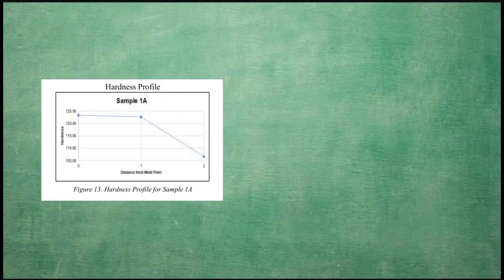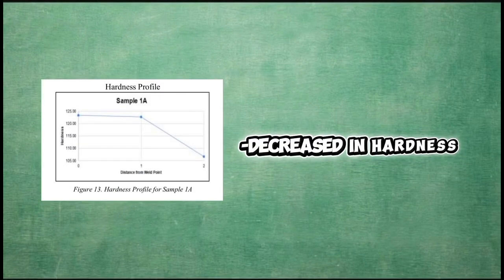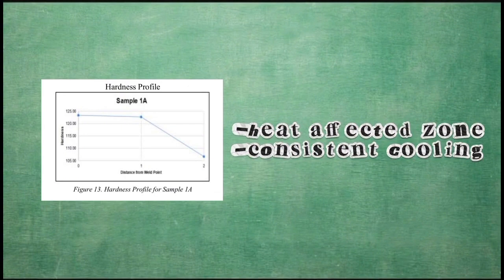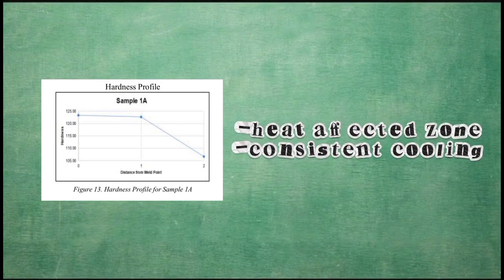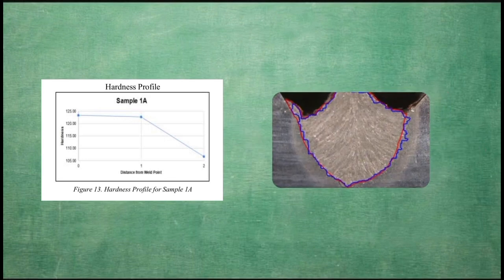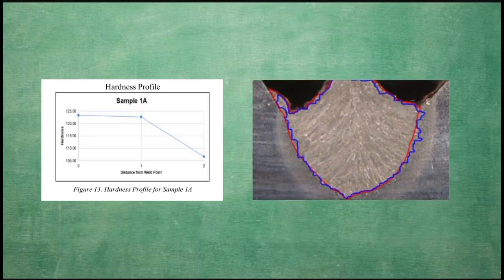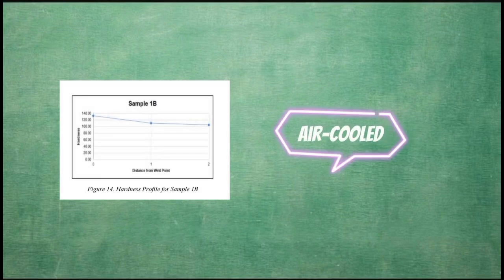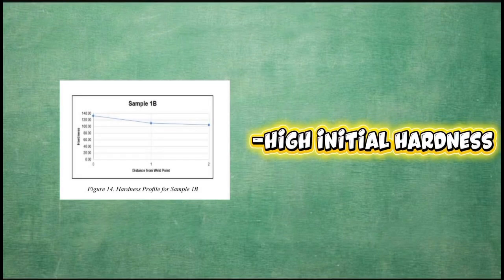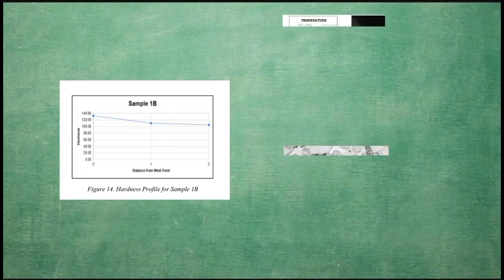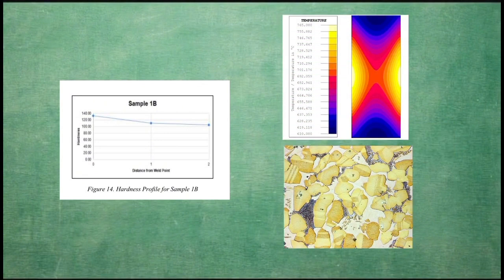For the discussion of results, we have sample 1A, air-cooled, which showed a gradual decrease in hardness from the weld zone to the base metal, indicating a uniform heat-affected zone and consistent cooling behavior. The weld area exhibited higher hardness due to thermal exposure, while the regions farther away became softer because of reduced heat influence. Sample 1B, air-cooled, exhibited a high initial hardness near the weld followed by a sharp decrease, suggesting a steeper thermal gradient and faster microstructural transition.